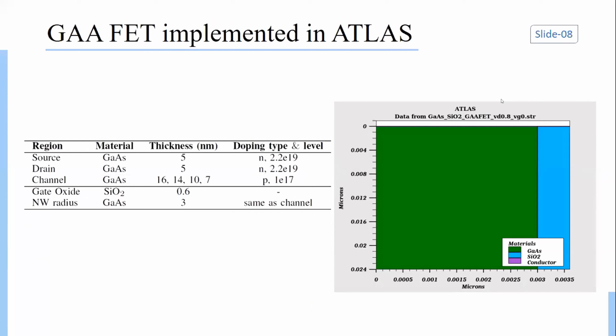Here is our structural information and TCAD generated 2D slice of a GAAFET. From the table we can see that the source and drain material is gallium arsenide. Also channel material is gallium arsenide. For source and drain we used 5 nanometer of channel thickness, and for channel we analyzed 16, 14, 10 and 7 nanometer channel thickness. Our gate oxide was 0.6 nanometer and nanowire radius is 3 nanometer. Our doping information is also here.